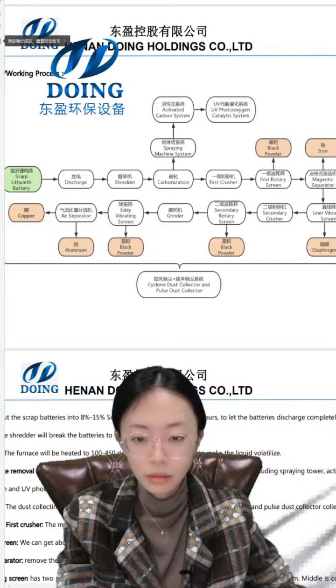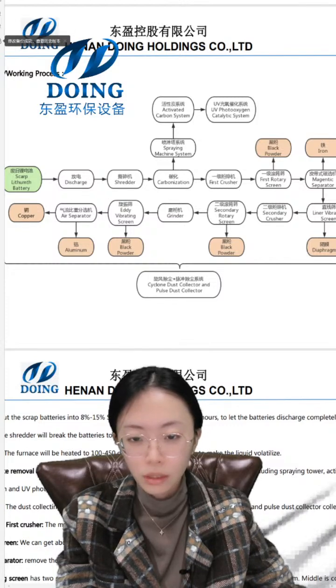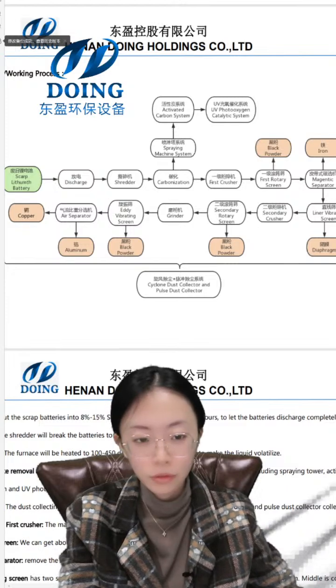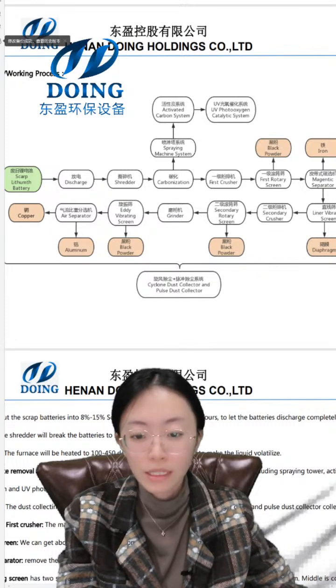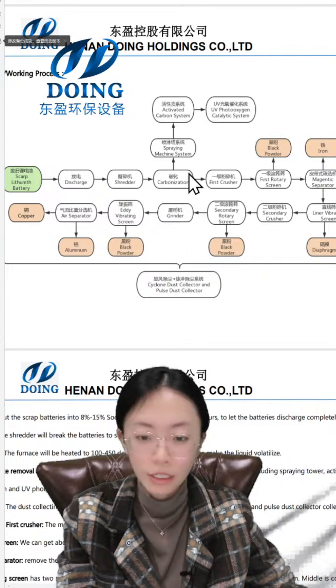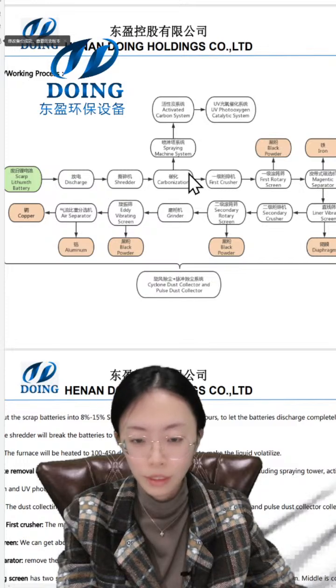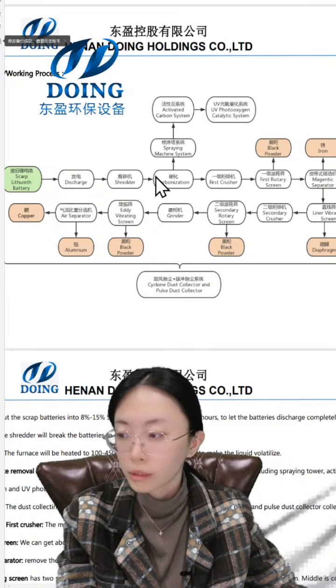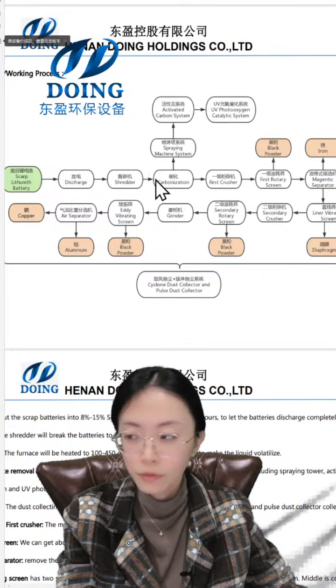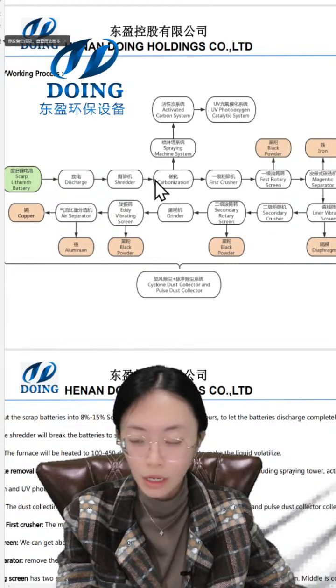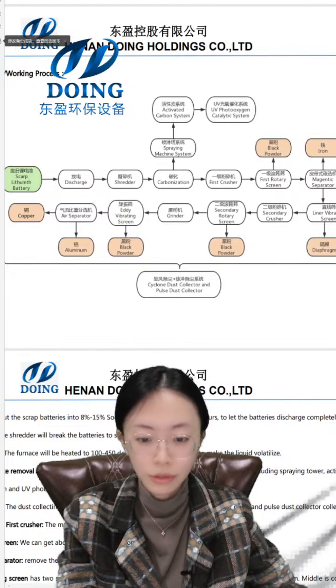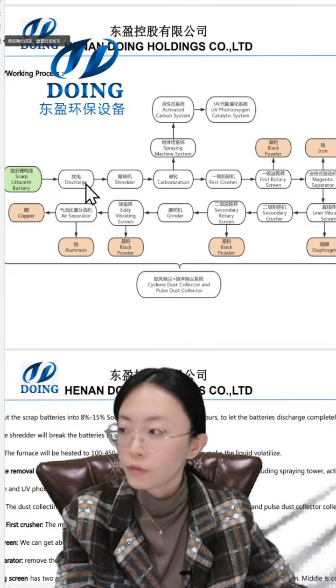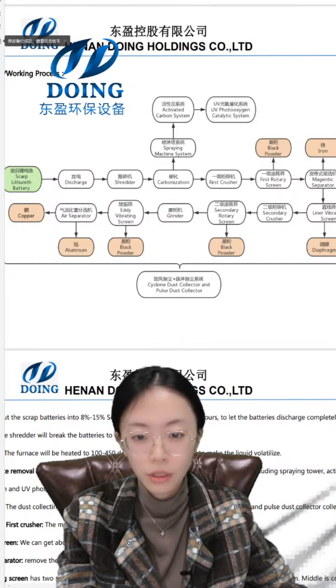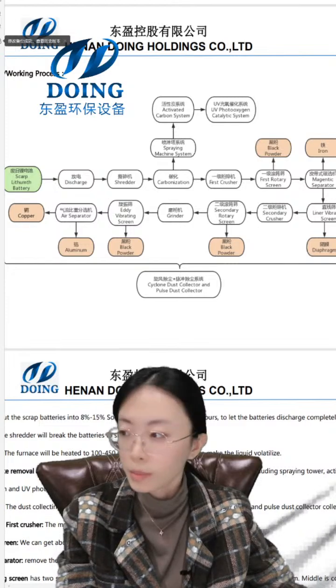If you need more capacity, more than 500 kilograms each hour, we suggest you use this combination furnace, or what we call a drying machine, to dry the material in this step. If you don't have many raw materials to process each hour, you can just dry them naturally. Then after discharging, our raw material will go into the double shaft shredder.